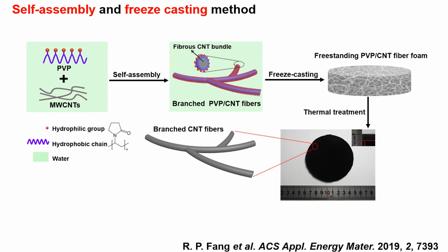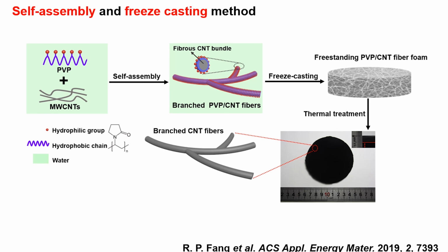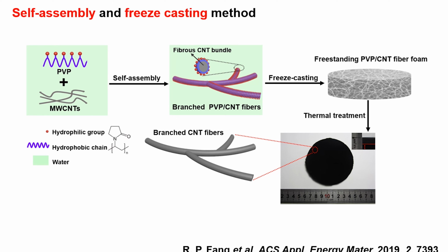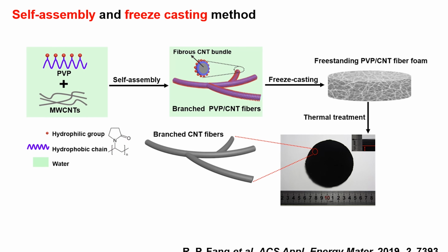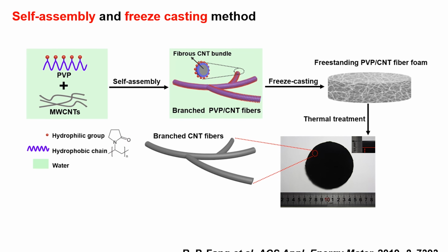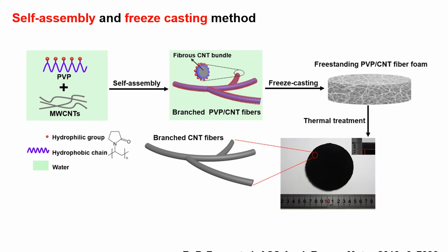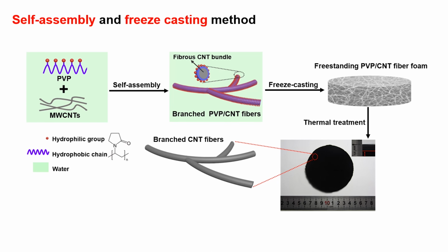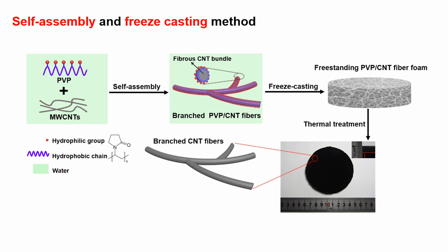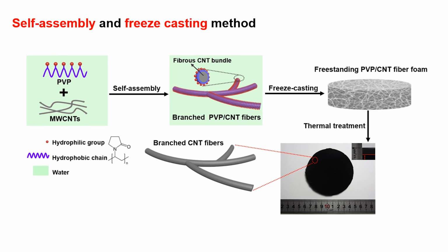The first example is the branched fibrous carbon nanotube sponge. Here we use carbon nanotubes and PVP as the precursor to obtain a freestanding sponge structure through a self-assembly and freeze-casting method.